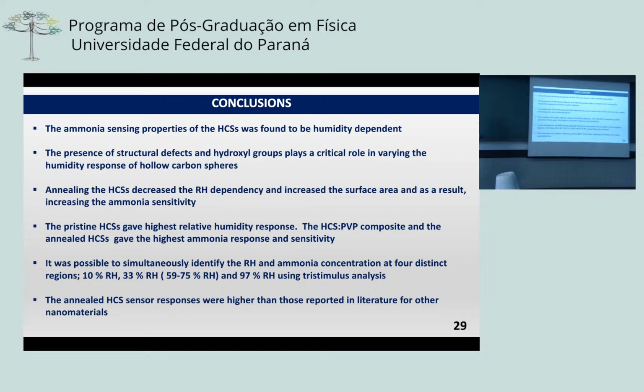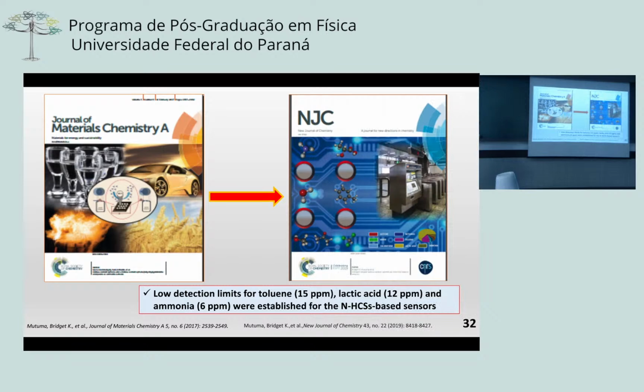And we are able to simultaneously identify relative humidity and ammonia concentration in 4 different regions using the tri-stimulus analysis. And these responses were higher than those reported in literature. So this was the first work on hollow carbon, and it was really amazing. And through that collaboration, we were able to publish the work, which was in a hot paper collection in 2017.